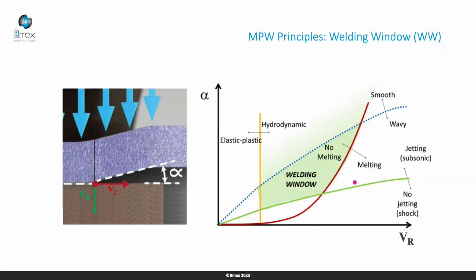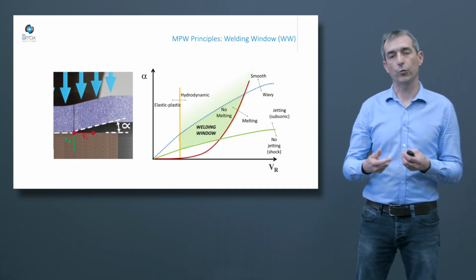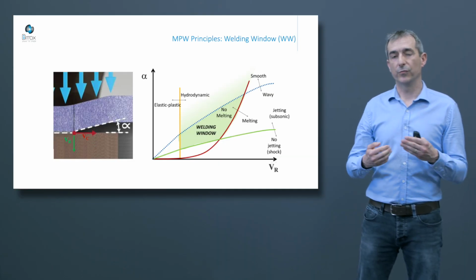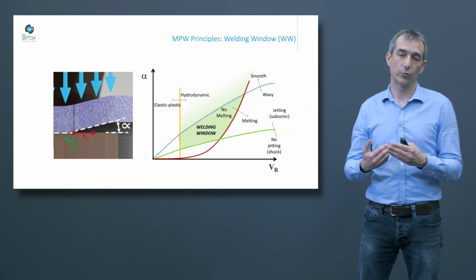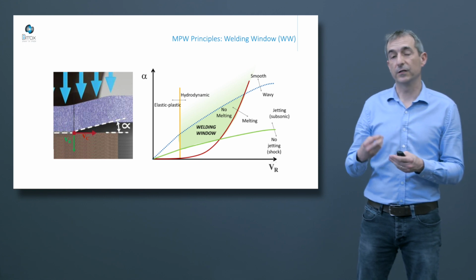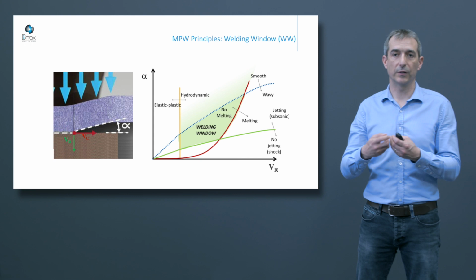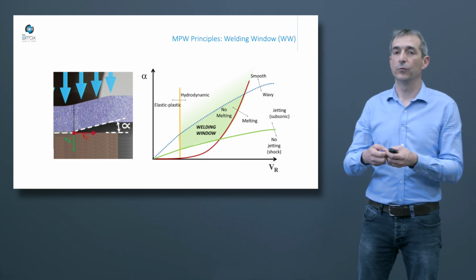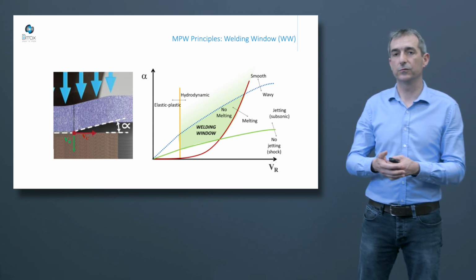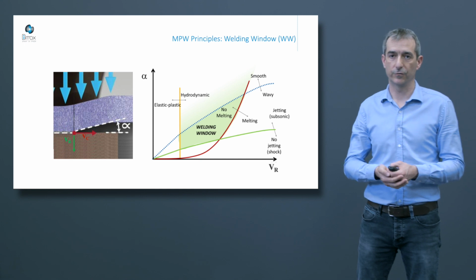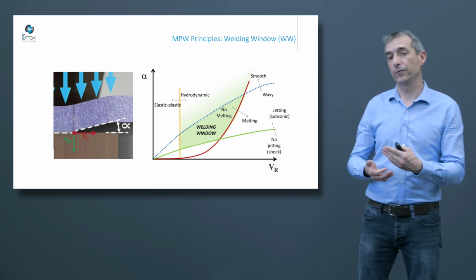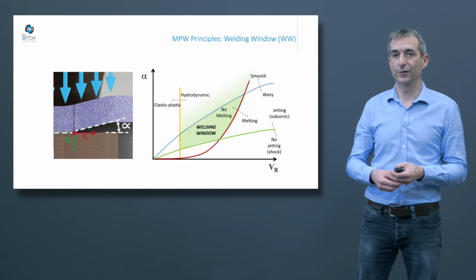The second limit is the sound speed in the materials. It's the green line. If the contact closing is too fast, we create a shock wave in the material, and the bounce back and the effect of this shock wave can destroy the weld. Even if we have a good pressure and temperature to create a weld, we can destroy it due to the bounce back and the reflection of shock waves. It's the second boundary of the welding window.